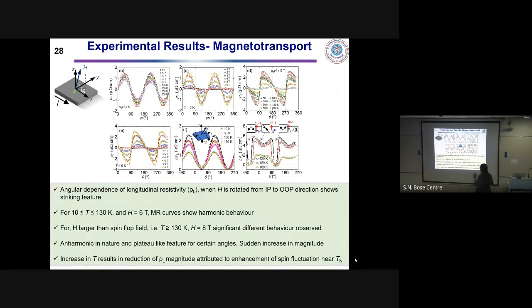With this, we wanted to explore further, and we measured the angular dependence of the longitudinal resistivity rho L with respect to theta, that is, when the magnetic field is rotated from in plane to the out-of-plane direction. It shows a striking behavior. As you can see, for 10 Kelvin, 50 and 100 Kelvin, and even for 130 Kelvin, when the applied magnetic field is 6 Tesla or less, we see a harmonic behavior in delta rho L. However, when the magnetic field was increased to 8 Tesla and the temperature to 130 Kelvin and above, it got modified to give this kind of a feature.